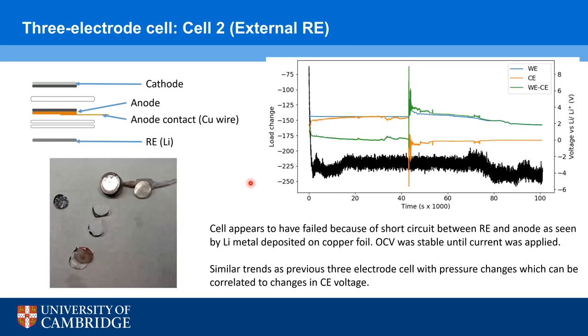So then we tried again with a different configuration, this time with the reference electrode at the bottom, external and underneath the full cell. This time the open circuit voltages for the NMC in blue and the silicon in orange were a bit more steady, but then when we applied the current after 12 hours, we had a short circuit, and we can see that the voltage fell below zero. This indicates that there is a lot of current being applied. As we opened up the cell, we saw that the lithium metal electrode here, the shiny one, had been stripped. When we compare that to how a normal lithium metal electrode looks within a battery, it has a much duller color. So this shiny color indicates that it did strip and expose fresh surface and deposited on the back of the copper current collector of the anode.